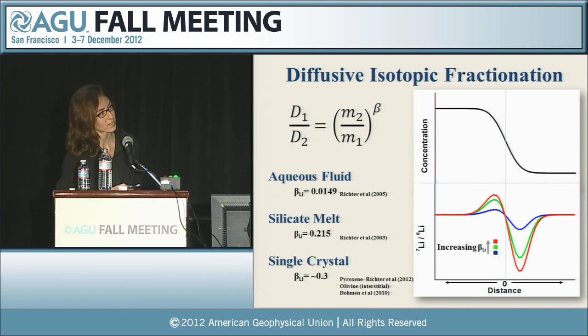What diffusive isotopic fractionation usually looks like is shown on the right here. So here we have concentration and 7 lithium divided by 6 lithium as a function of distance, where 0 is the point of the original interface between the high concentration side and the low concentration side of the diffusion couple. So as lithium diffuses from the left side to the right side here, a greater flux of lithium-6 will move over to the right side, and so that will cause an overabundance of lithium-6 just to the right of the original interface, and that will decrease the 7:6 ratio.